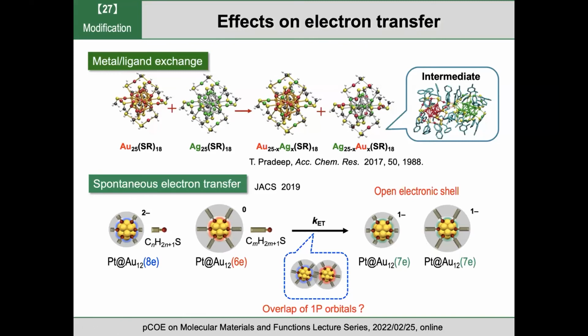So how about the stability of your 7 electron cluster compared to the 6 electron or 8 electron cluster? Stability against what? These clusters are formed as a stable species, nearly 100%. If we mix these two 1 to 1, we have a 1 to 1 7 electron system in a stable form. Okay, it's very interesting. Thank you.